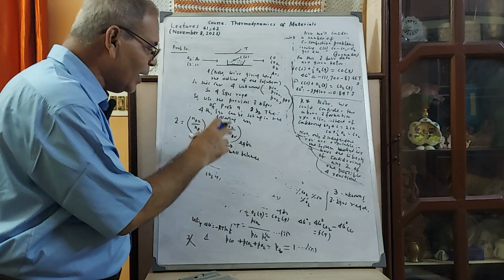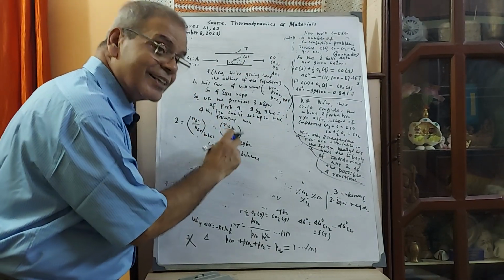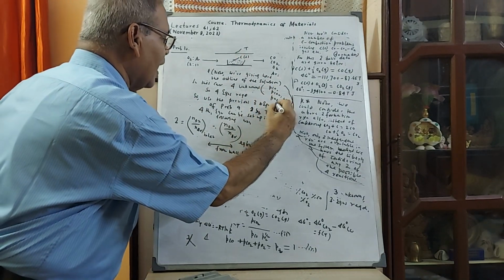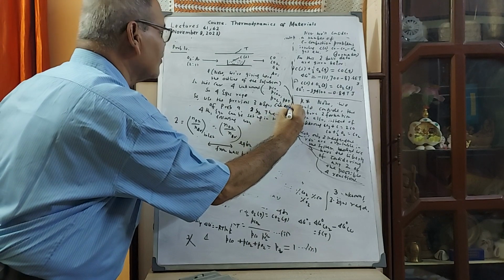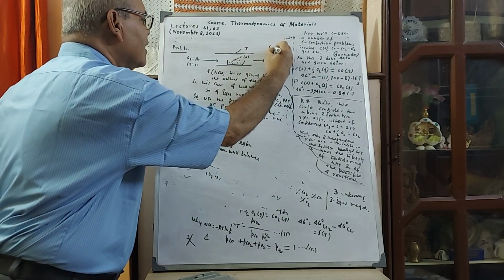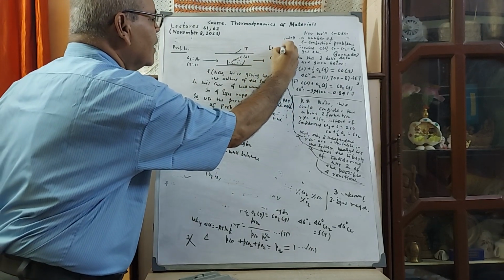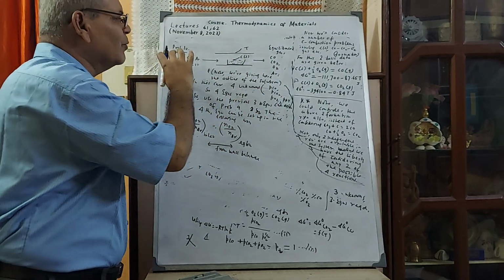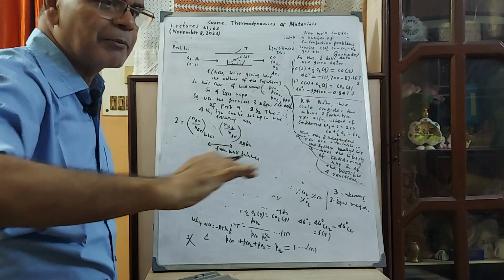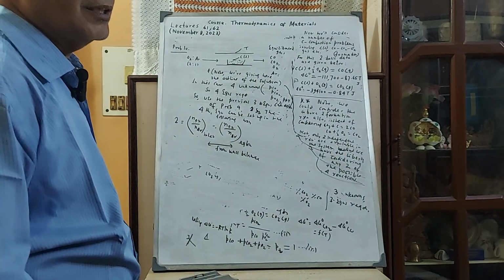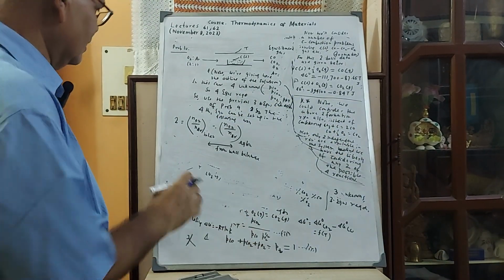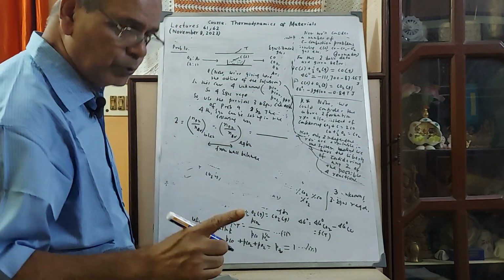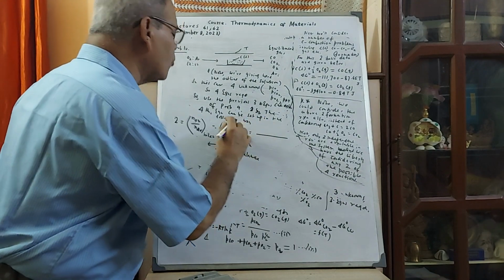So this at our interest is where? Which one? Here, this or this? Equilibrium, sir. We are considering these at equilibrium, right? Again, you always see the equilibrated gas. Equilibrated gas means you have to assume that when it is going over the carbon bed, it is attaining equilibrium before leaving the reactor. So from mass balance, how much? Now this you have to write. Follow this. This is new to you, the first time.